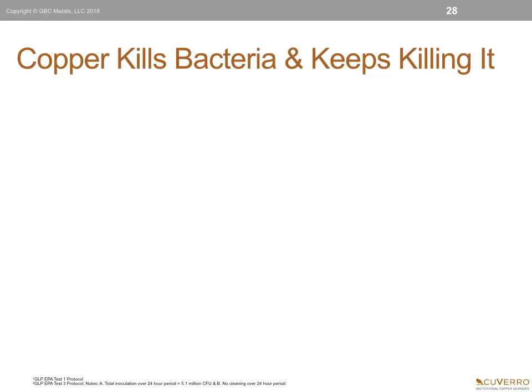Here, the repeated contamination test is illustrated. Copper and stainless steel were re-inoculated eight times, each inoculation at 640,000 colony-forming units. After a 24-hour period, without any cleaning between inoculations, copper exhibited the ability to continuously kill bacteria, while stainless steel significantly gained bacteria over that same 24-hour period. This is the most important of the three EPA tests conducted. Copper is EPA-registered to make public health claims, while bacteria thrives on stainless steel surfaces.